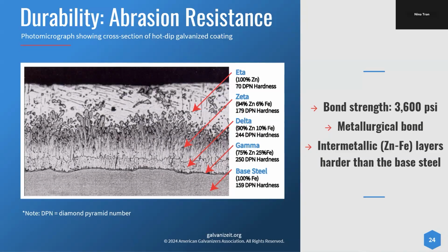If you notice the gamma, delta, zeta are all actually a mixture of zinc and iron. Gamma is 75-25, delta 90-10, zeta 94-6. But they all have a DPN hardness number of above 159. So actually making the alloy layers harder and stronger than the base steel itself. So it just gives it that extra abrasion resistance. And also you can literally see the metallurgical bond happening.